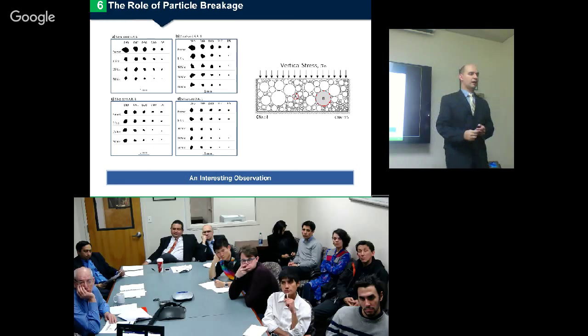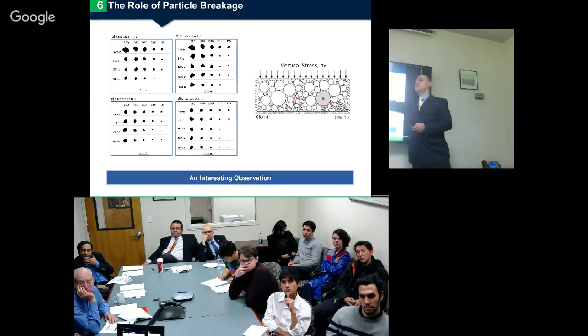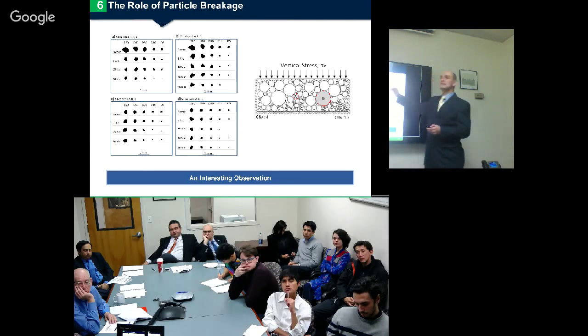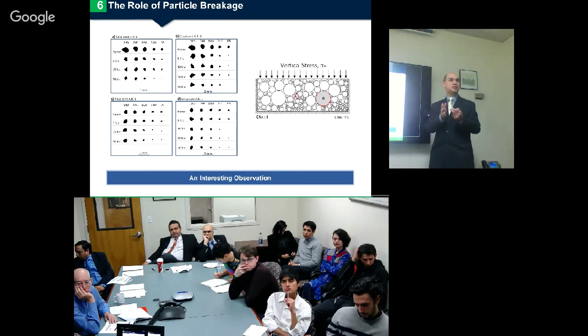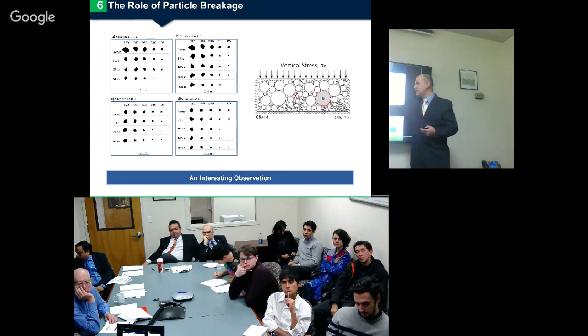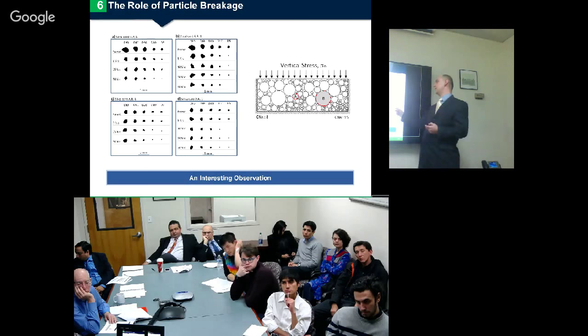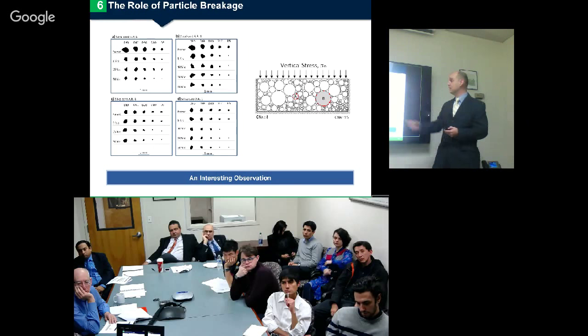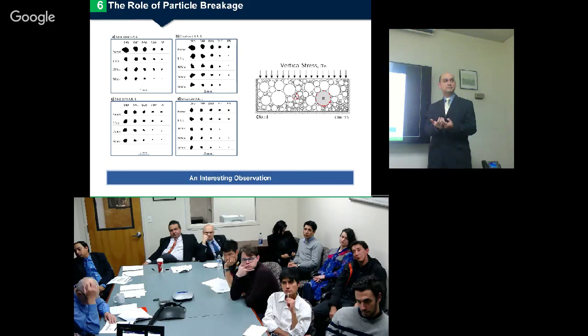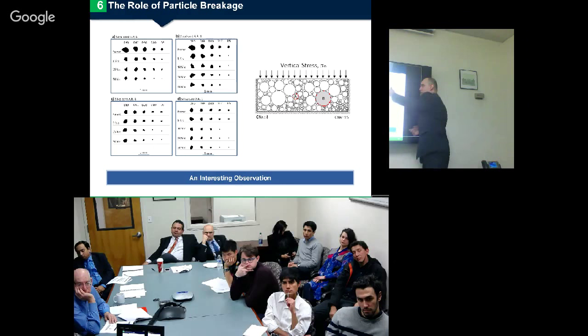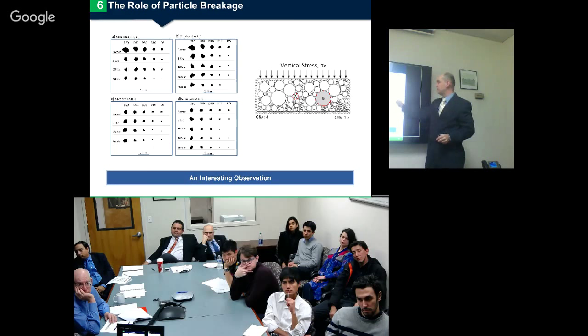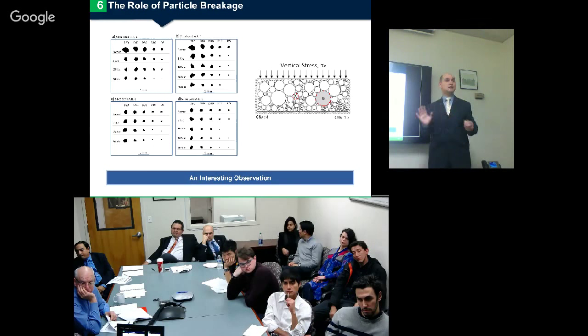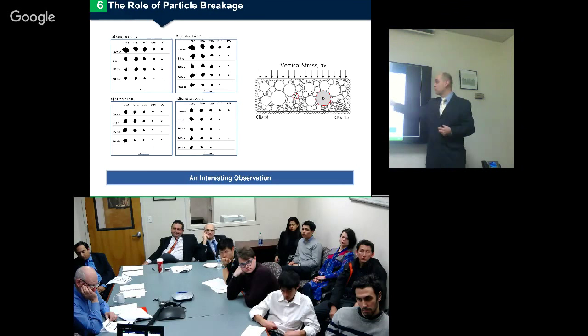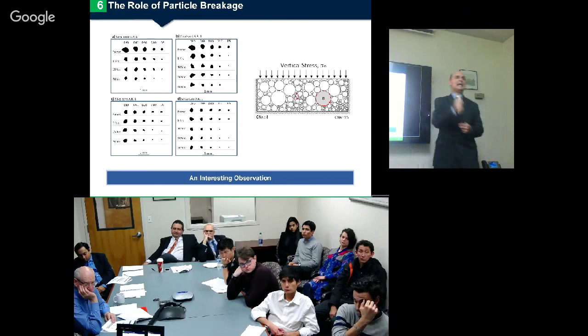Obviously, this is an ideal condition. In the actual mold, we have materials of different sizes, right? There is an actual load being applied. We have these boundary conditions that prevent radial deformation, and all of this external load is going to be transferred through force chains that form internally. Now, this is the coordination number of particle A, and this is the coordination number of particle B. I counted A here and B here. Why? This particle is larger than this one. It has more neighbors, right? So when it has more neighbors, the energy is transferred more evenly. The load comes from the top and is transferred to all the different neighbors or contact points, not in the same magnitude, but it transfers that energy more than when you have a smaller particle that obviously has fewer contact points.